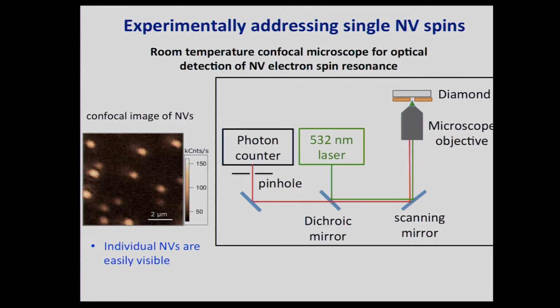Okay, so I can briefly tell you about how these are experimentally addressed. As I mentioned, it's a pretty simple setup. We just build our own confocal microscope where we illuminate the NV center through a high numerical aperture microscope objective. We illuminate the diamond sample with green light. The NVs in turn fluoresce. They emit photons in the red. And that is collected by some very sensitive photodetectors.